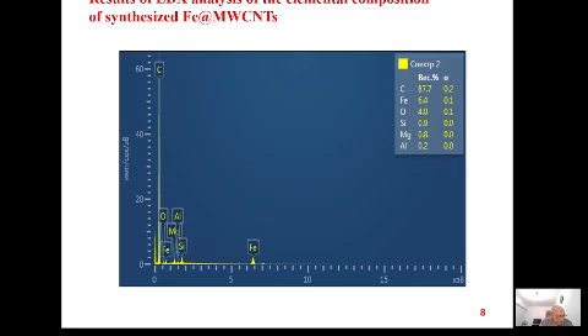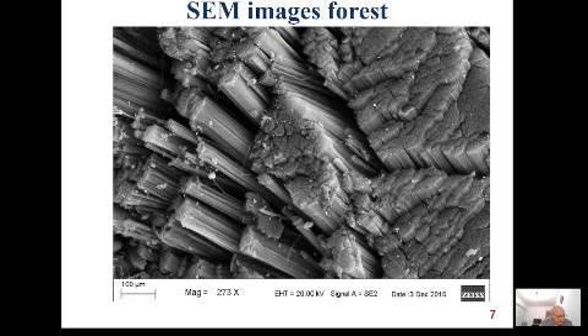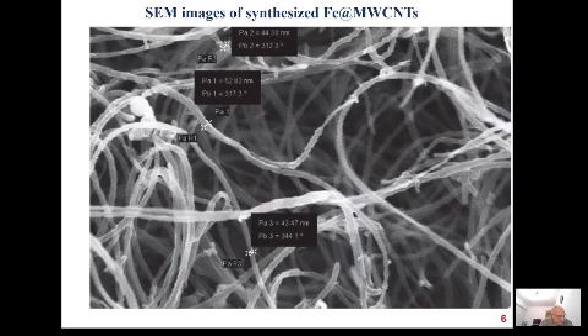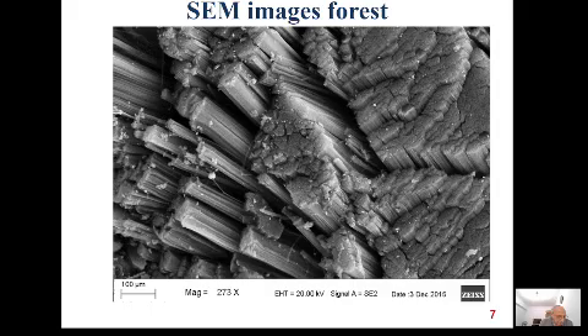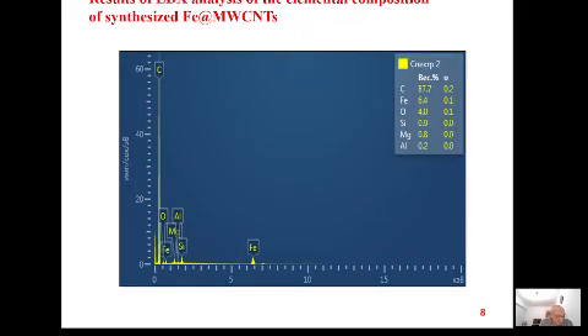It is seen from this snapshot that the carbon nanotubes correspond in shape and size to the standard requirements. Slide number 6 and 7. The diameters of the carbon nanotubes are about 44, 52, and 43 nanometers. That matches well with standard requirements. As for elemental composition, the contents of carbon, iron, and oxygen are prevailing, constituting the major components of multi-walled carbon nanotubes.